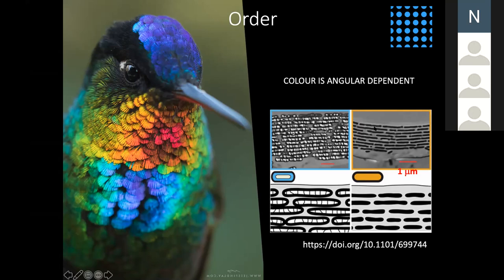You can see this layering that is on the order of a few hundred nanometers periodicity, that is comparable with the wavelength of the light, such that you can create this interference phenomena. And similar to Bragg scattering, maybe you have done it in your course, when you do X-ray diffraction, you know that the diffraction peak corresponds to different angle, to different orientation of the crystal. This is really similar. It's a photonic crystal, it's not like a molecular crystal. So in the same way, you can have this diffraction effect, this optical response, in this case with visible light, a different coloration depending on the angle that you look at it.